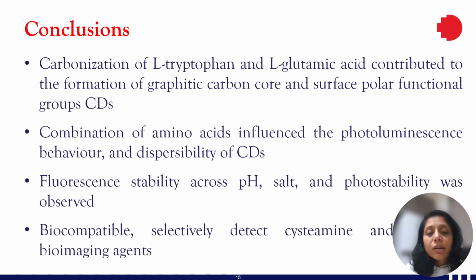So to conclude, carbonization of tryptophan and glutamic acid contributed to the formation of a graphitic carbon core and surface polar functional groups on the carbon dots. And the combination of amino acids influenced the photoluminescence behavior and dispersibility of these carbon dots. These carbon dots were stable across various pH and salt concentrations, and photostability was observed. These carbon dots also demonstrated biocompatibility, selectively detect cysteamine, and have the potential to be utilized as bioimaging agents.